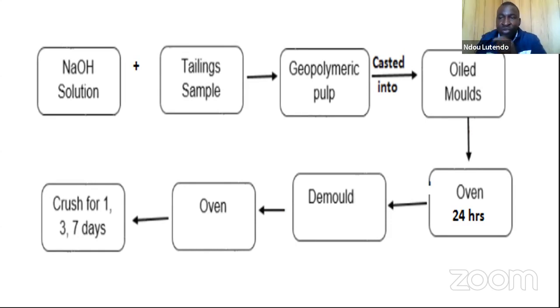And in the oven, that's when you demold, for them to actually get that curing temperature nice in the oven. And then you crush them. So crushing is basically a mechanical process, which is a geotechnical technique for you to actually get the strength. That's why with cement, they tell you that this cement, PPC cement, has a strength of 42.5. It's because they've put it under crushing. You'll actually hear more of this as we go forward.